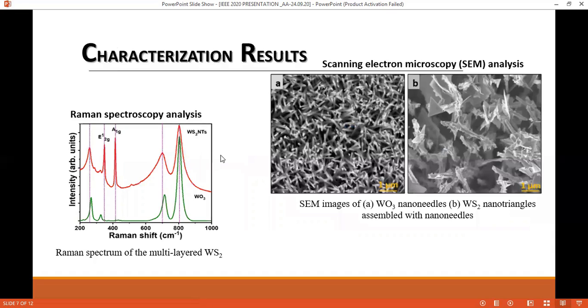Now, after the synthesis, the grown nanomaterial is characterized using scanning electron microscopy and Raman spectroscopy. As shown in figure A, tungsten trioxide grown by the AACVD technique consisted of thin and elongated nanoneedles which were randomly oriented. After the sulfurization process, the morphology of these nanoneedles changes completely to form a continuous film of tungsten disulfide having a mixed morphology of nanotriangles and nanoneedles.